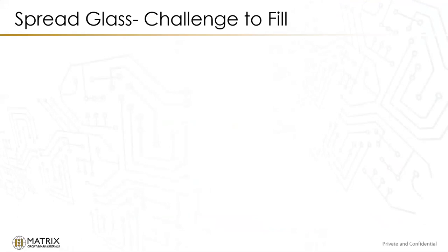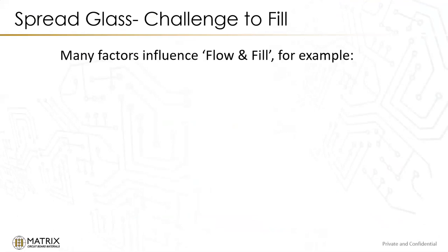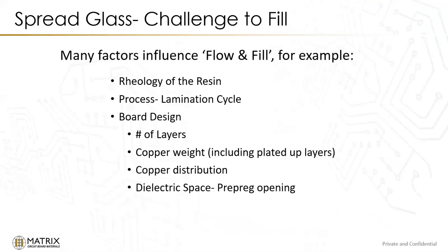The lower flowing resin systems present one of the challenges, but there's a lot of factors that influence the flow and the fill. And of course, the rheology is a part of it, the process, the lamination cycle. The board design itself has a lot to do with it, number of layers, the copper weight, of course, how thick are those copper layers, and the copper distribution. And then many designers want to have a very thin dielectric space, and of course that then starts getting into the prepreg. So I'm not talking about all these other factors. That could be topics for another discussion. We'll focus in on the impact and what we can do with the prepreg itself.